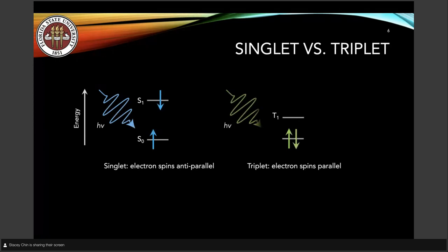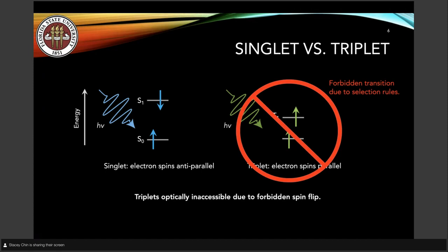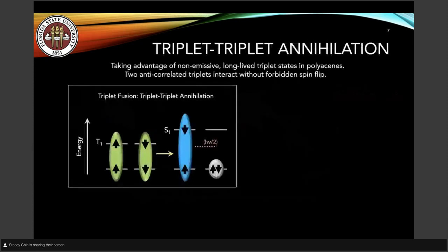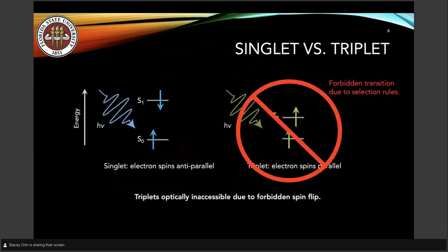The triplet state, however, would require not just the excitation to a higher lying state, but also the spin flip. And this is a forbidden transition due to selection rules, and therefore triplets are optically inaccessible because you'd have to excite to a higher lying state and do the spin flip at the same time. And therefore, sorry, we can't really access these very well. So yes, moving on.